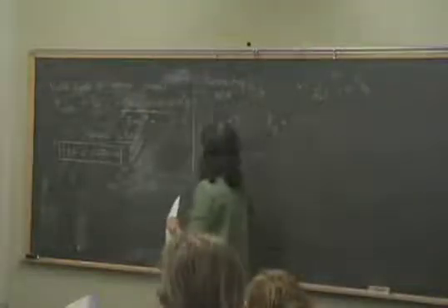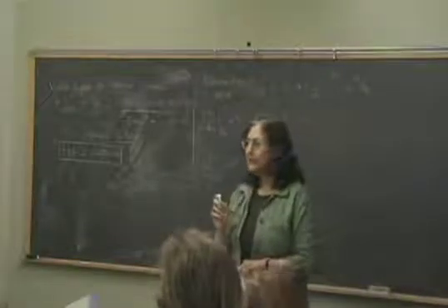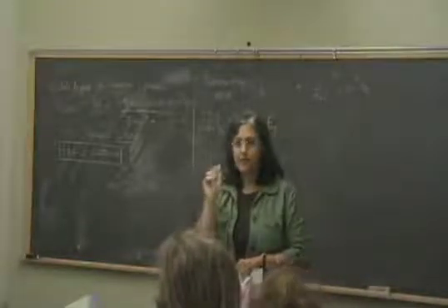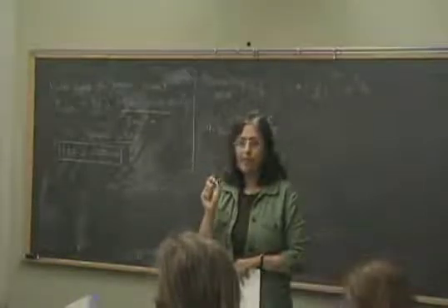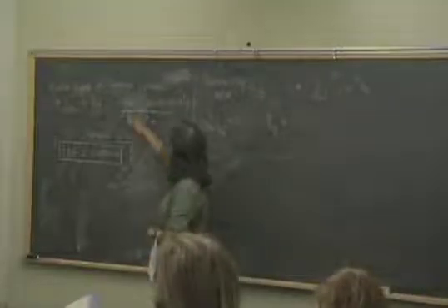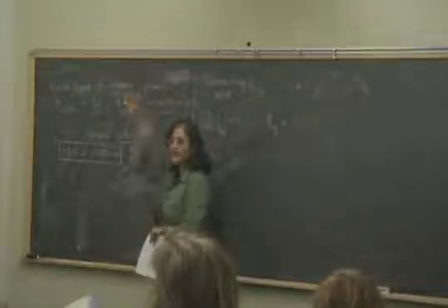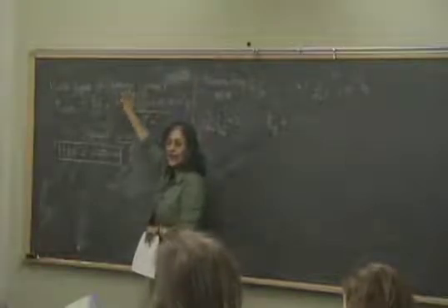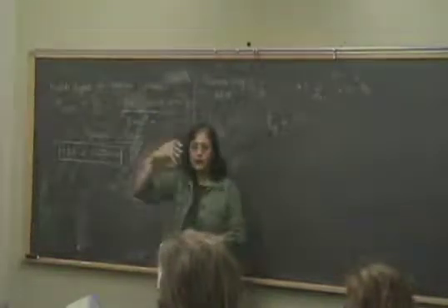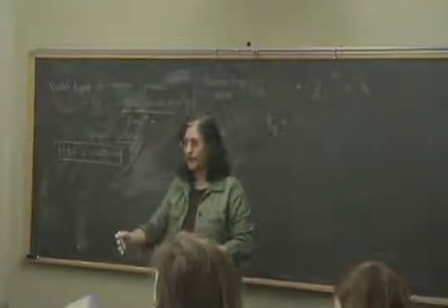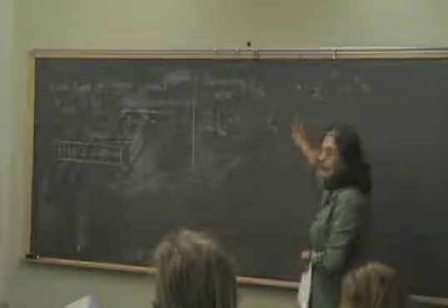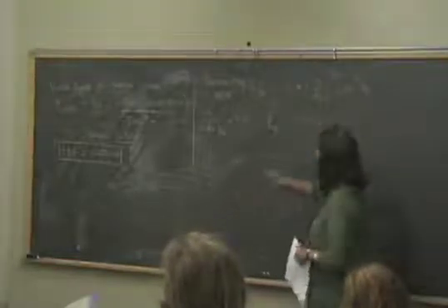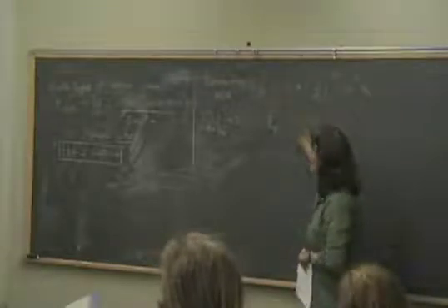So just to be sure everyone is on the same page, what we are trying to address is this Egyptian cup, where there was absorption by gold particles at a wavelength of about 500 nanometers. And I will show you the data again when I can pull down my slides. So when the cup was tested, the absorption was around 500 nanometers. Now we want to see where this is coming from. Okay, so here we have gold. We have treated gold as a free electron gas. That free electron gas essentially oscillates at a plasma frequency and gives us an energy of 9.1 electron volts, not 2.5.